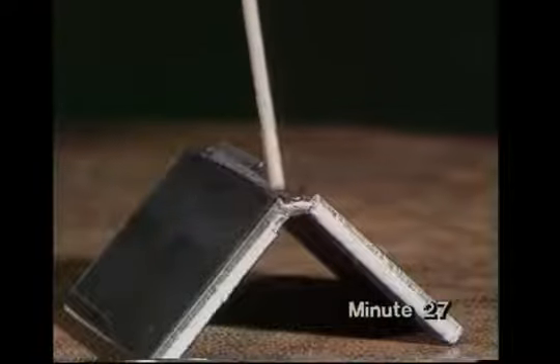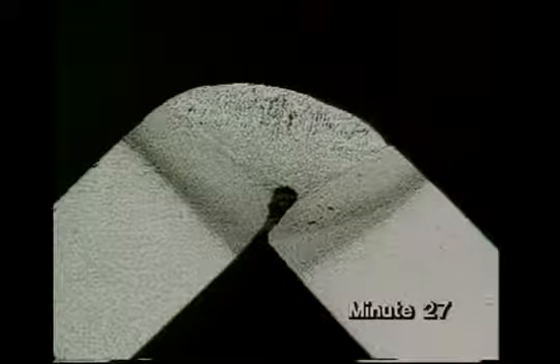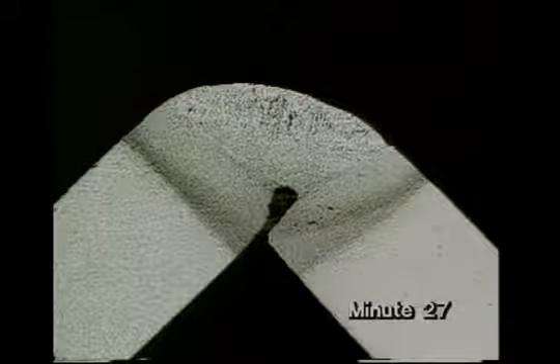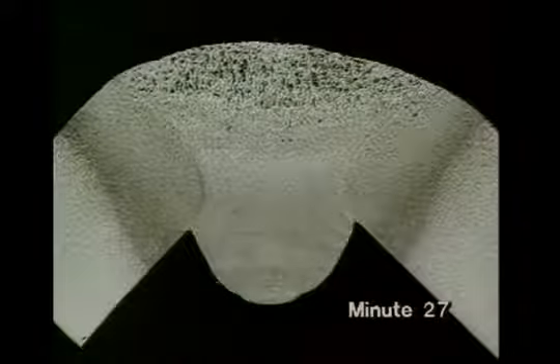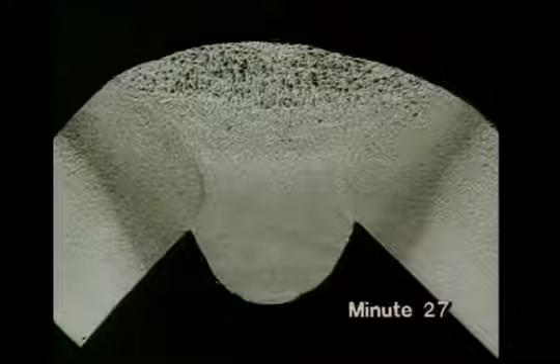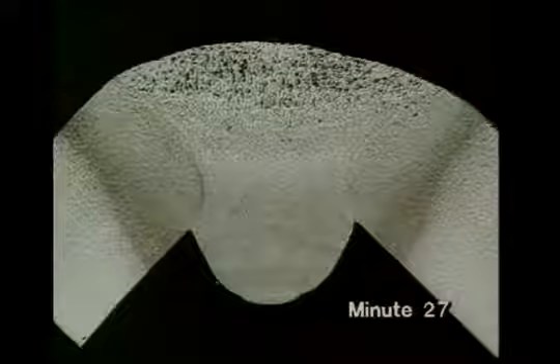As you won't have filled the joint with metal, make a second run with weaving. Pause at the sides for good results. The macro section shows that the weld metal fills the joint with a reasonably smooth top and bottom surface. This, on the other hand, had the plates overlapping before welding, and the weld hasn't penetrated right through the joint. Here, the gap was too big, and the molten metal has penetrated too much. In fact, it could have melted right through and left a hole.